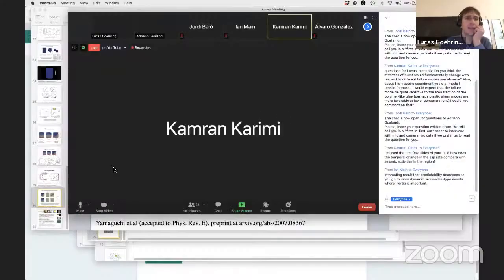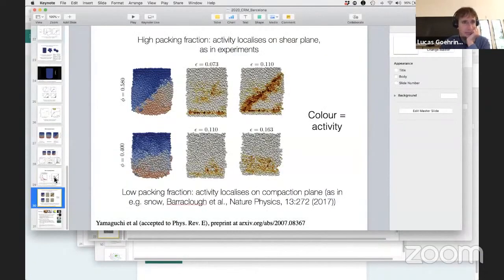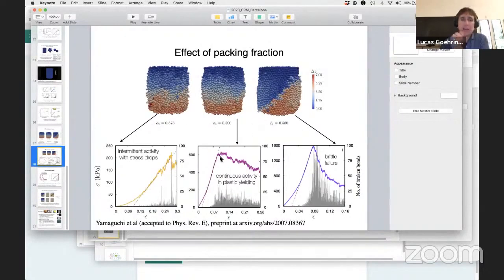So there was a slide where you showed different failure modes toward the end of your talk. Do you think that if you look at the statistics of bursts, that will fundamentally change with respect to these different failure modes? So we suspect yes, and that's one reason why we plotted them in this way. But the sample size was actually tuned to that of the experiment, which was built around the X-ray tomogram size. So the sample size is only about 3,000 to 5,000 particles. We suspect yes, and we can see that in the statistics here.